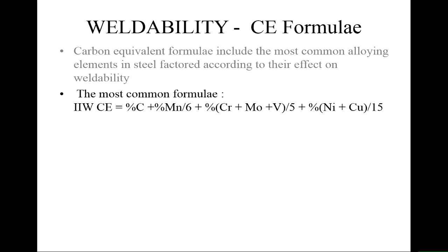So a typical constructional steel might have a small amount of nickel, molybdenum, manganese in it. So the basic carbon content is 0.2%, but the carbon equivalent is about 0.5%. And it's much harder to weld than you think because of all these other elements. And the killer one really is manganese, because that's added in the primary steelworks. So when we talk about carbon steel, what we should really say is carbon manganese steel, because every steel has manganese in it. It's a deoxidant and it deals with the sulfur in the steel, but it affects the weldability. And so you need to know the manganese content.